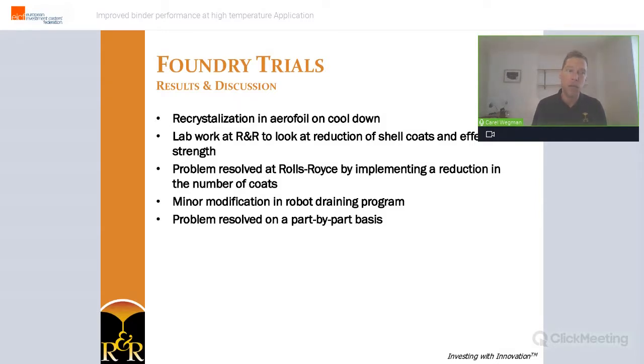So R&R went back to the lab and we continued investigating what would be the effect of further shell coat reductions. And luckily, the problem was in the end resolved by further altering the number of coats on the mold, as well as a change of the robot draining programs. And the issues had to be resolved on a part-by-part basis. But I think this is inherent to the development of any new slurry or shell system in a foundry. So it was considered normal and successful in the end.